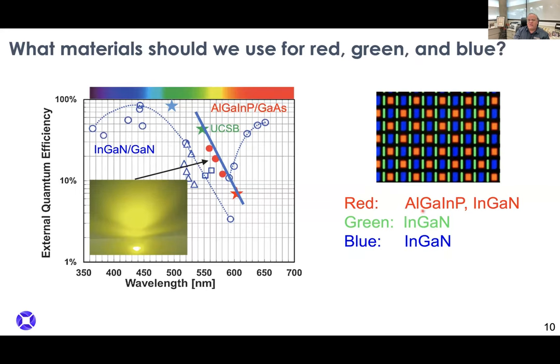But what we now think we want to do is achieve very high efficiency red in the indium gallium nitride. And if we can do that, then we don't need to marry these two material systems, but we can put it all together. And this currently shows you where we are in the efficiencies in what I'd call large scale LEDs. But even in the red now, we've gotten to 6%. And we need to get that to about 15% to defeat this other gallium arsenide based material.